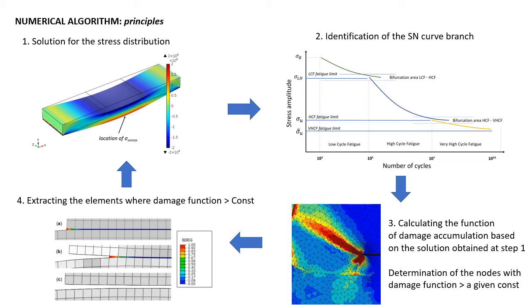At the last step, all elements where the damage function exceeds the given value are deleted from the numerical model. So this procedure can lead to introducing stress concentration factors to the model. After that, the elastic analysis is repeated for the numerical model with the deleted elements, and this procedure will be repeated up to the final fracture of the structure element.